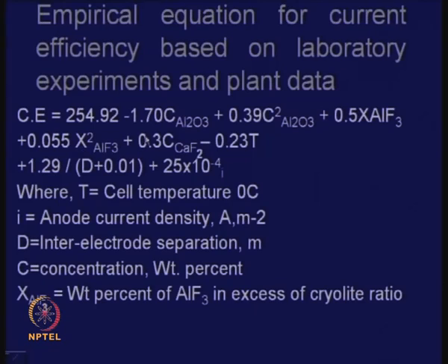Current efficiency will increase with aluminum fluoride addition, both are plus. Current efficiency will increase with calcium fluoride addition. Current efficiency will decrease with temperature obviously, and there are some dimensional things also like inter-electrode separation. If the inter-electrode separation increases, this term will increase, therefore, current efficiency will drop.